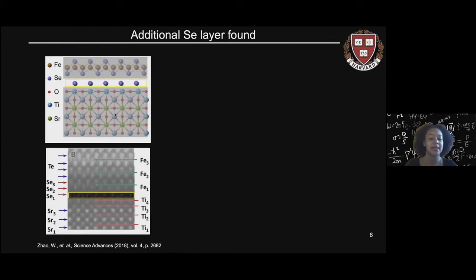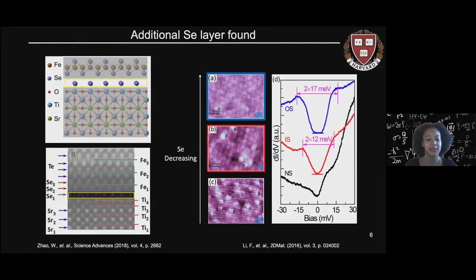So the question becomes, how might this excess selenium impact the superconductivity? Well, a separate study employed STM imaging and superconducting gap measurements to show that a decreased presence of selenium in the iron selenide increases the superconducting band gap. So as we move up the panels, you'll see the sample contains less and less selenium, and you'll see this directly correlates with a widening superconducting gap. This suggests that the extra selenium layer might be screening the phonon modes and therefore influence the superconductivity. Or additionally, the selenium dopants in the film might add hole carriers that might destroy the superconductivity.